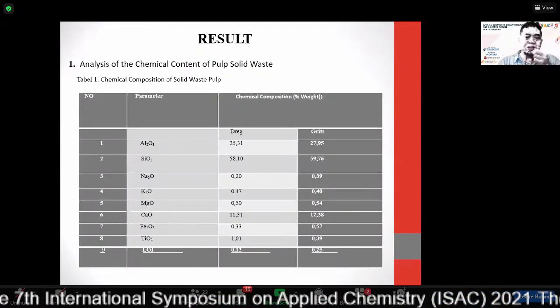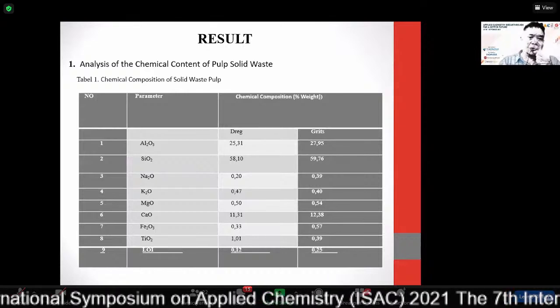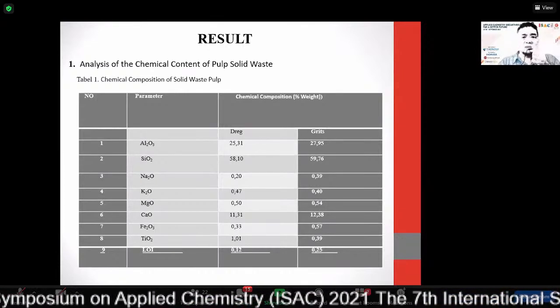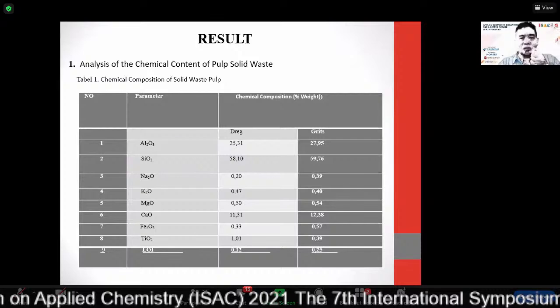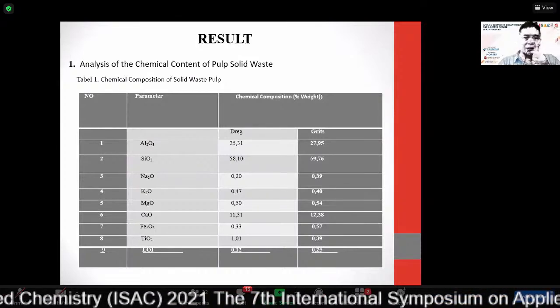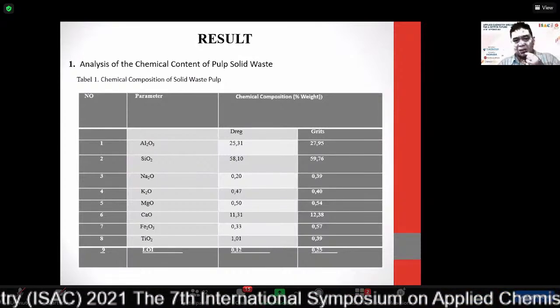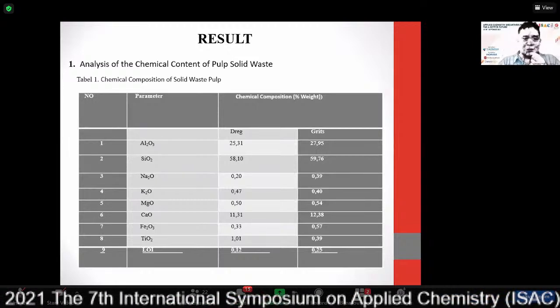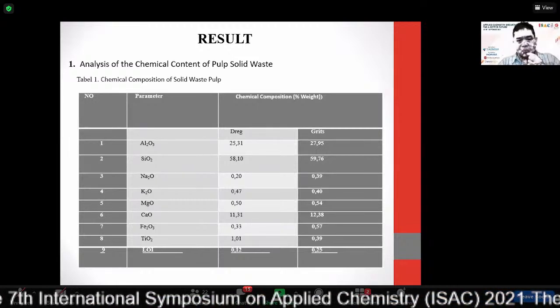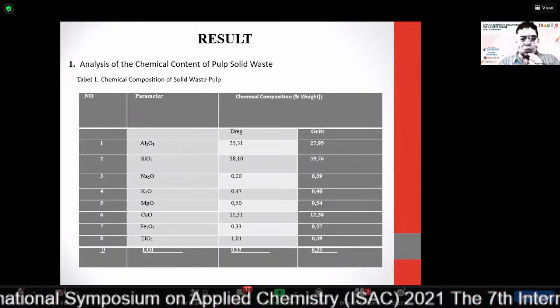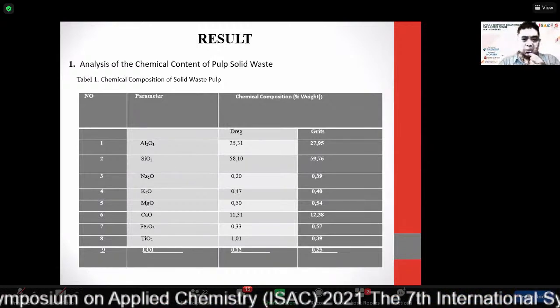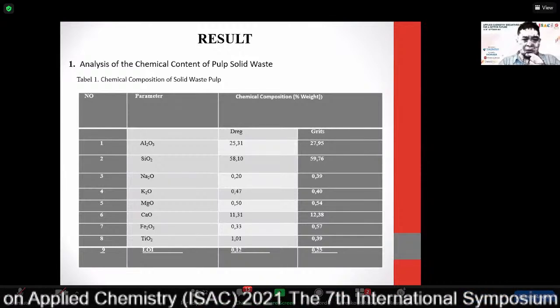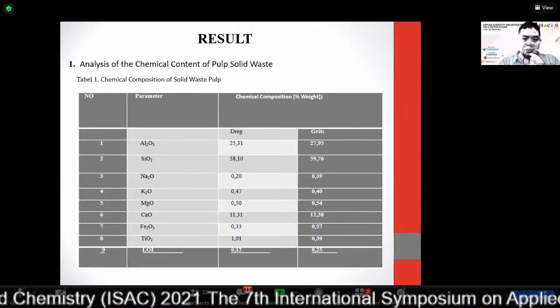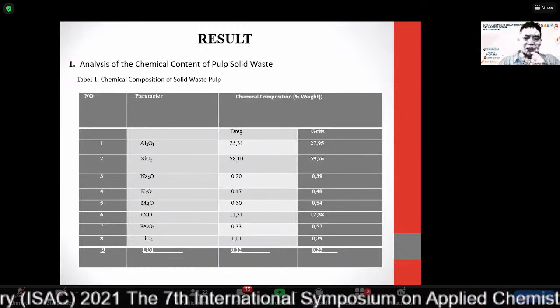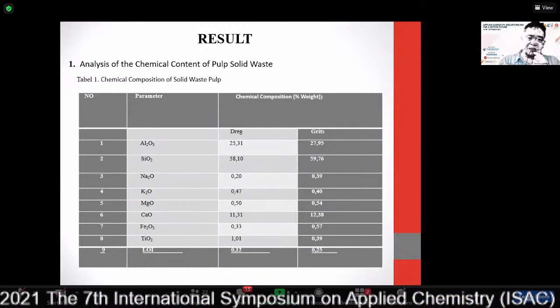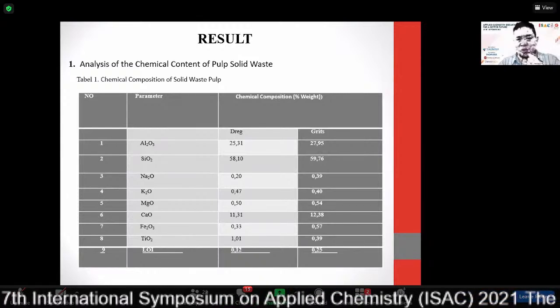This is the result of chemical content from analysis with XRF. This result shows that the content of silica oxide, aluminum oxide, calcium oxide, and ferro oxide is the main component in the bricks, in the solid waste.